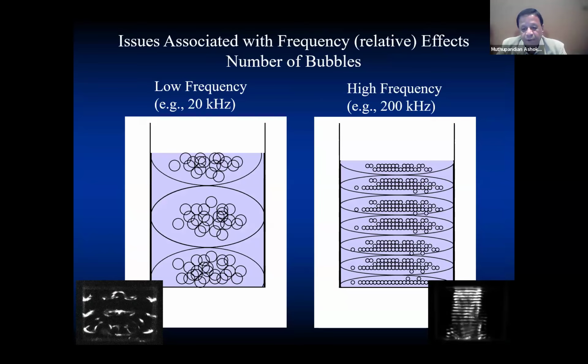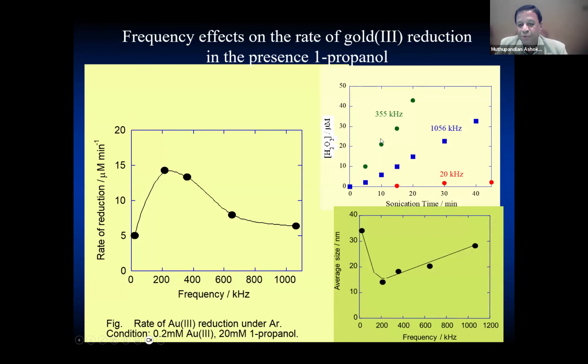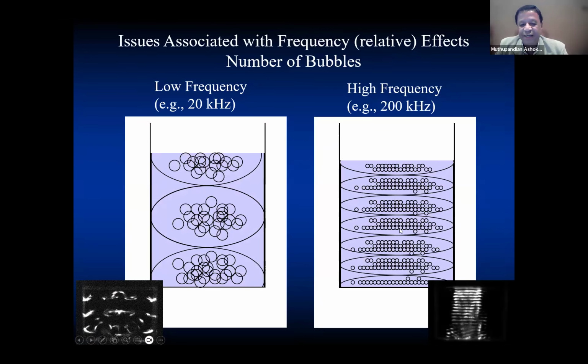I don't want to go too much into the details of the mechanism because we don't have time. I have to cover quite a bit of slides. But basically, I can explain why we produce a large amount of radicals around 300 kilohertz. It is a combination of the number of bubbles. For example, as physicists, you know that as you go to higher and higher frequency, the wavelength decreases. When the wavelength decreases, the number of standing waves in a given liquid increases. As you increase the number of standing waves, the number of antinodes in the liquid increases. When you increase the number of antinodes, you increase the number of cavitation bubbles. If you increase the number of cavitation bubbles, you increase the number of radicals produced.